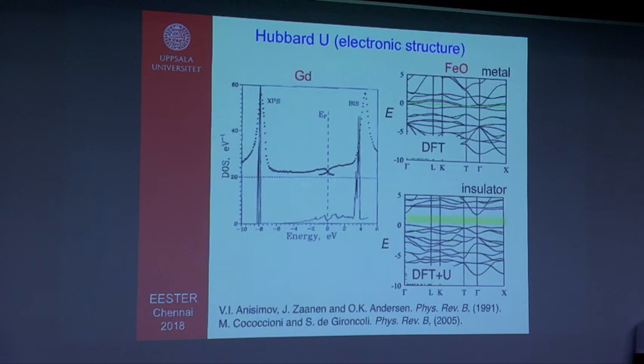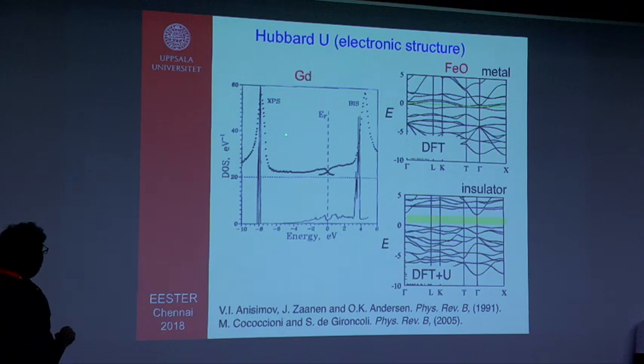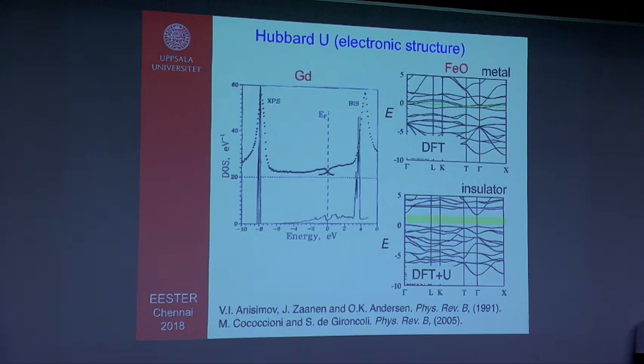Let's look into the results if you do an LDA plus U calculation. So this is gadolinium, ferromagnetic, 293 Kelvin, density of states versus the experimental spectra. You see that this is the XPS, which gives you the occupied part of the density of states, and this is the BIS spectra, which gives you the unoccupied part. And you see that if you do the correction on the f states, the f states more or less come to the correct position. So this was one of our earlier successes.